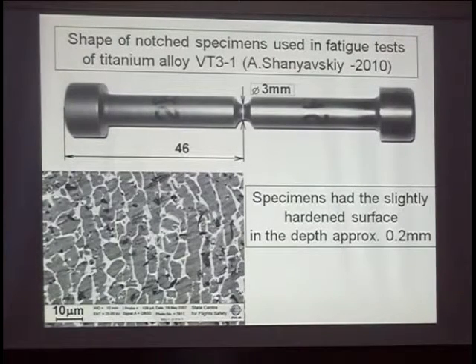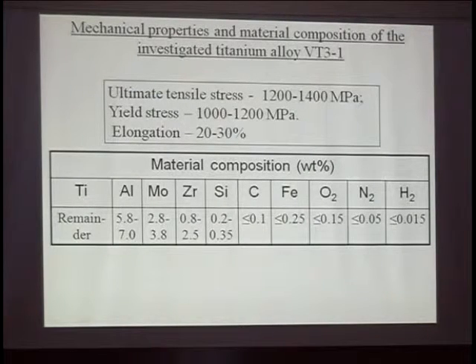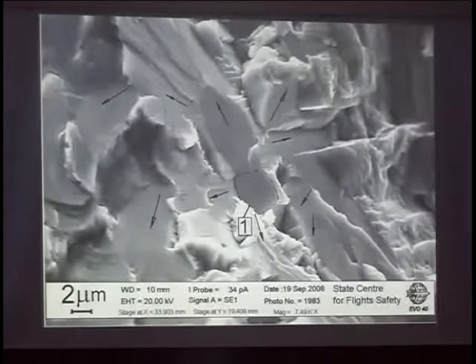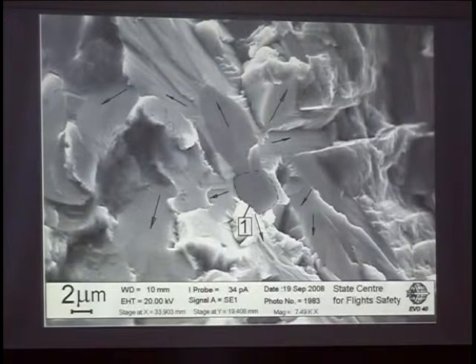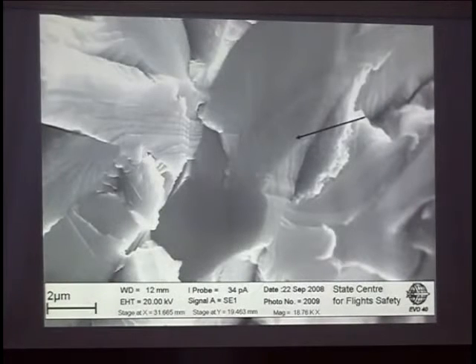First of all, I would like to introduce our knowledge about material cracking as a model. One of the notched specimens was investigated, with this material structure, these material properties and chemical composition, and based on the acoustic emission approach and fractographic analysis, we discovered a specific area of material cracking as the origin with a very flat surface. This surface, we think, forms because of twisting and compression of material,